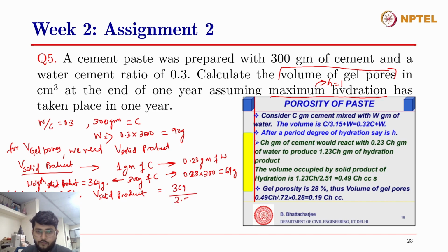So 300 grams of cement will react with 69 grams of water, and as mass is conserved, the weight of the solid hydration product will be 369 grams, right? Now we know that the specific gravity of solid hydration products, as discussed in the class notes, is 2.51. We can use this to find the volume of the solid hydration product, and that will be 369 divided by 2.51, which comes out to be 147 cm³.